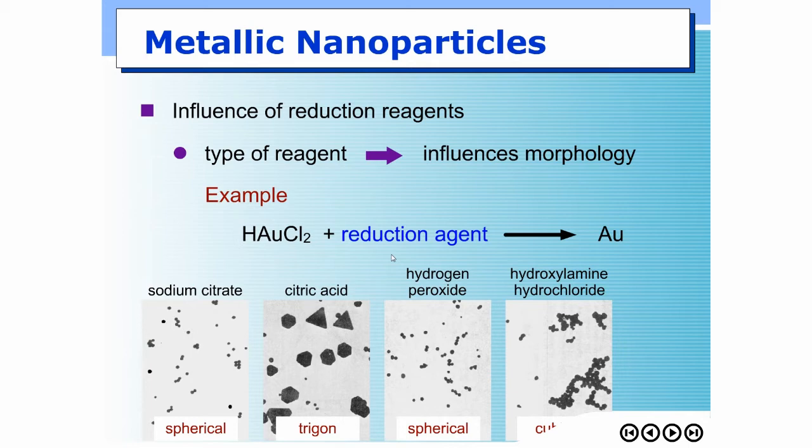In growth, the stronger the reducing agent, if you have a strong reducing agent, that means you have a high concentration of growth species. Suppose you have a high concentration of growth species left for the growth process, then there will be a high gradient of growth species concentration between the bulk liquid and the surface of the particles that gives you a high flux of diffusion of growth species, and that would not give you the diffusion growth that we want.